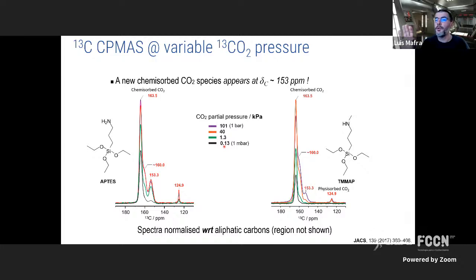This was the first publication showing variable pressure NMR, by the way, in the literature. And you can really see that at a very low pressure, depending on the type of amine you use, I just concentrate now on these two amines, primary and secondary.